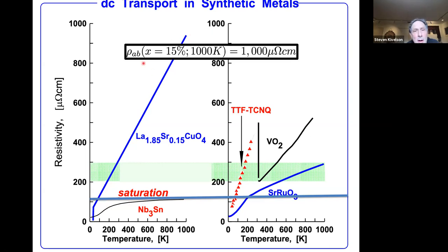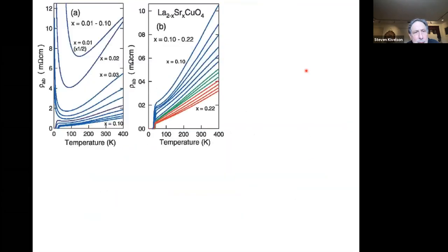So here at optimal doping and 1,000 Kelvin, we have a resistivity that's something like 1,000 microohm centimeters, something like an order of magnitude above the quantum of resistance.